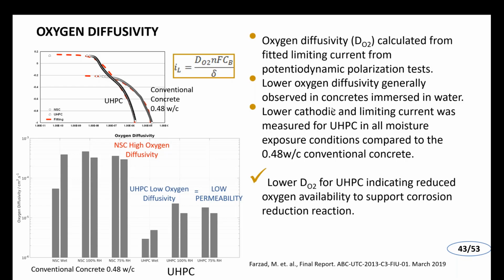Some other testing we did to look more specifically at gases, in particular oxygen. We looked at oxygen diffusivity in terms of electrochemical technique. I don't want to belabor too much on the technique itself, but we were able to identify through current that develops in the corrosion process the extent to which oxygen can develop. And so we identified this oxygen diffusivity, as we call it, comparing our conventional concrete in the graph in the bottom left.